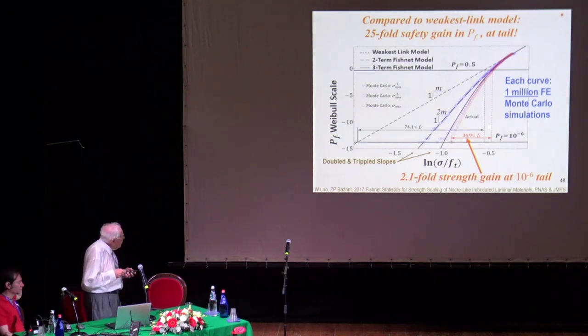You see, this difference is enormous. This is 75% of mean strength. This is 75. So that's more than 2 to 1. And you see that if you have this parallel coupling, in addition to weakest link, you enormously increase the strength of the material where it matters, for probability of 1 minus 10 power minus 6. You see this change. It's an enormous change. And that's what we should be looking for in design.